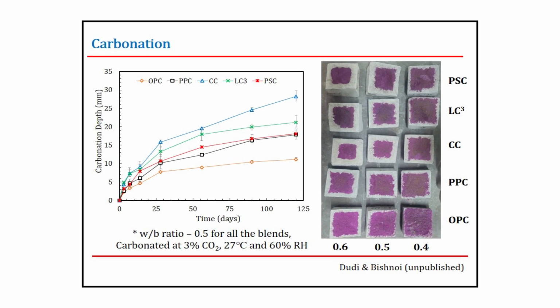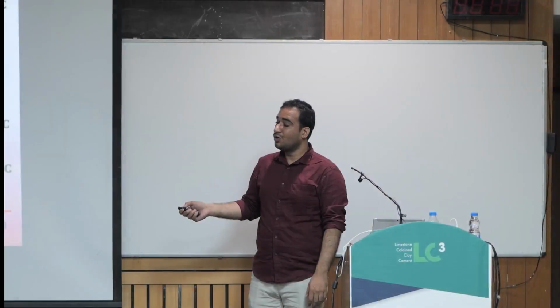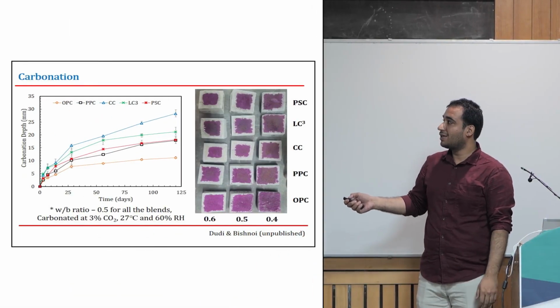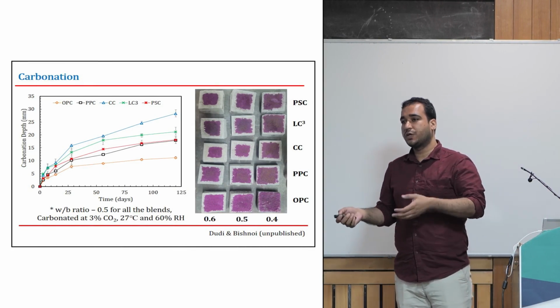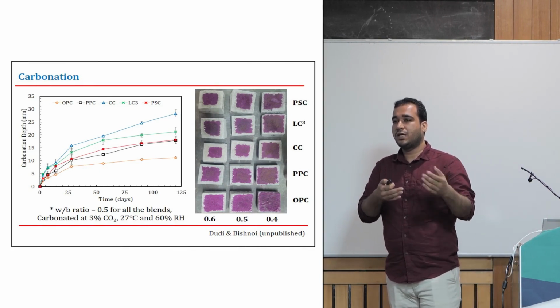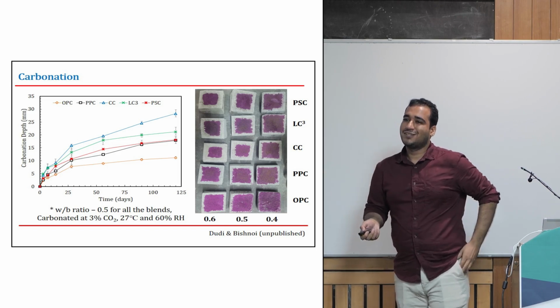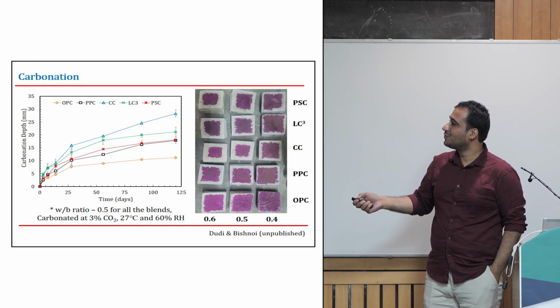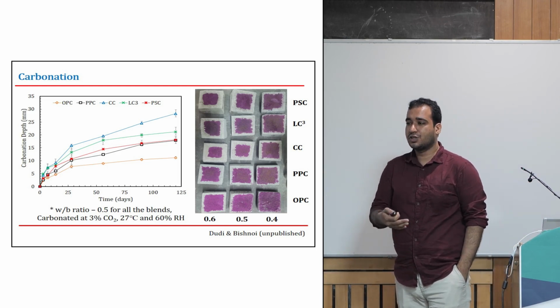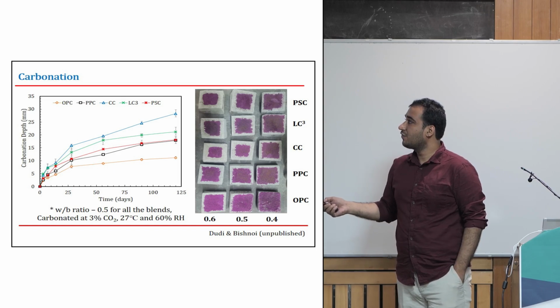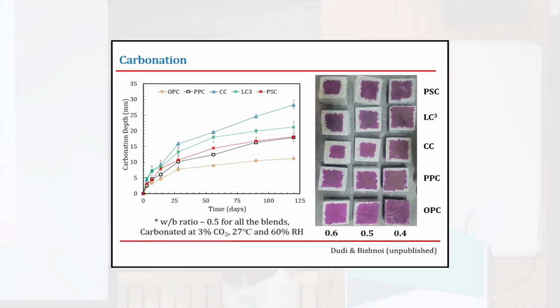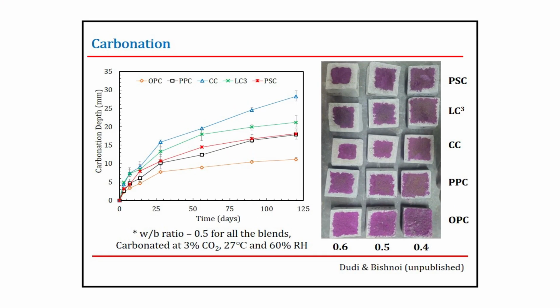So carbonation. If we see different carbonation species, we see that for different blends, the carbonation rate is different. In comparison to OPC, all the blended systems will have a high carbonation rate. The carbonation rate will be higher for blended systems because, in the blended systems, the Portlandite reacts with the SCMs to form the secondary hydration products, which leads to the consumption of calcium hydroxide. And this consumption of calcium hydroxide leads to a depletion of alkalinity in the systems, so we get a higher carbonation rate.